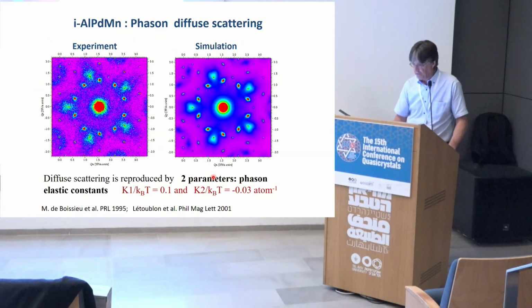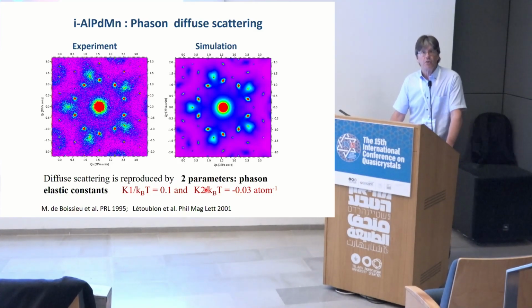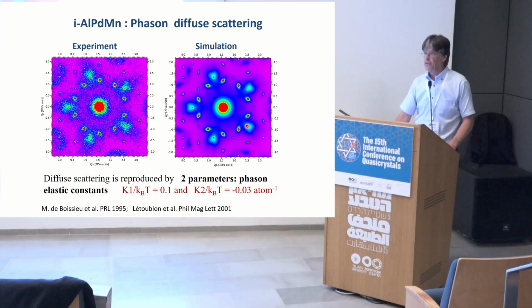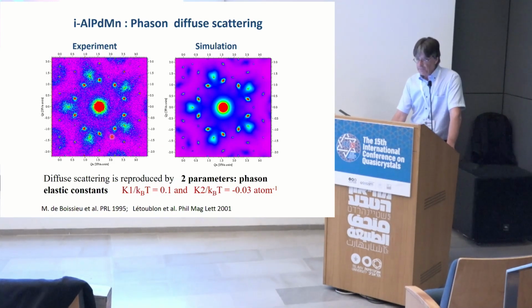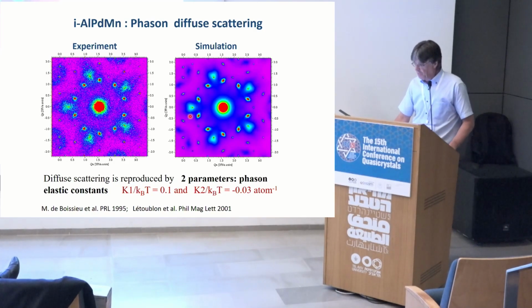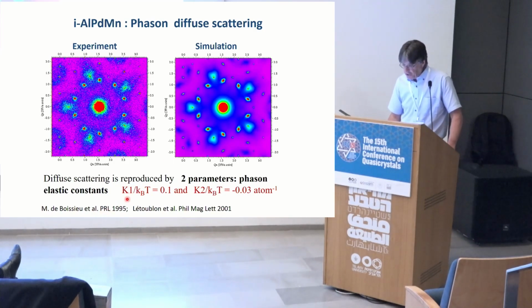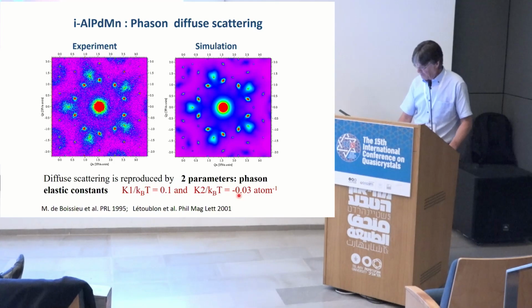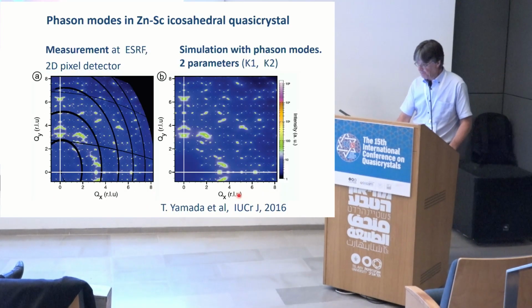Does not really matter. And indeed, in all quasicrystals, we could derive that the diffuse scattering which is observed can be described by these phason elastic constants. This is an example here in the aluminum palladium manganese case. We clearly see the experimental one and the nice reproduction using only two parameters, that's for the phason elastic constants.